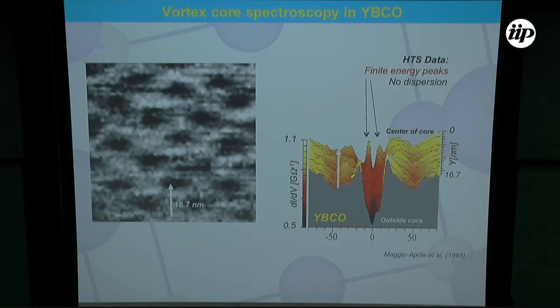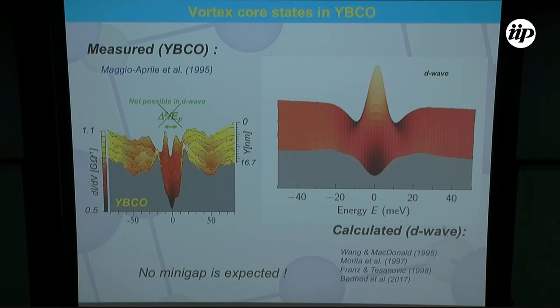Outside the vortex, we have a quite strong presence of coherence peaks, which are located at the position of the superconducting gap. But at the center of the core, you have this pair of peaks, which is located at 5 or 6 millivolts, and they don't disperse while crossing the vortex. So, okay, this was the measurement, and now the question is, what does the theory provide for the D-wave response of a vortex core? And this is the calculation, and you see that it's essentially similar to the S-wave situation, a zero bias anomaly and a dispersion, with the main difference that there are no bound states for a D-wave vortex, and it's not possible to associate these finite energy states with bound states in a D-wave superconductor.